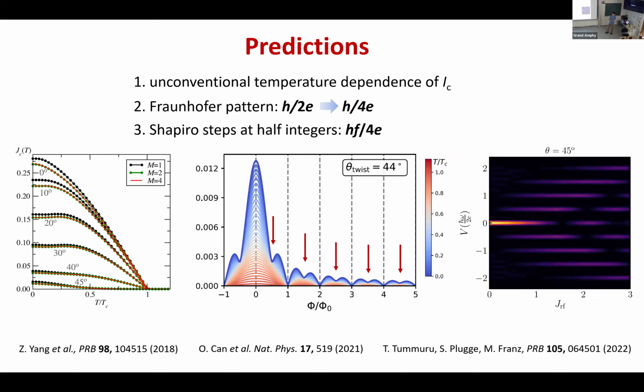One of them is that once you have 45 degrees, you don't have the Josephson tunneling from D-wave first order tunneling. But why we are seeing this Josephson coupling between the layers is because we have higher order tunneling. And this higher order tunneling comes with charge 4e instead of charge 2e. So this is one prediction: if we see charge 4e instead of charge 2e, then it may correspond to topological superconductivity, or what they call time reversal symmetry breaking superconductivity. And also there are not many other reasons for 4e, right? Yes. So then I will just show supporting evidence and also something we are doing that is trying to disprove this.